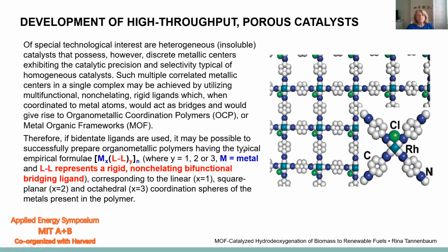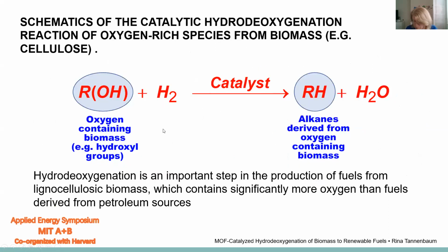So to develop the proper catalyst, again, we would like to have a heterogeneous, that means insoluble, catalyst that has, however, discrete metallic centers. That means that it's not just a metallic surface, where you have the metals on the surface, on the top layer, that are coordinatively unsaturated. They will be the active sites, but then the second and third layer in the metallic surface are going to participate much less in the process.